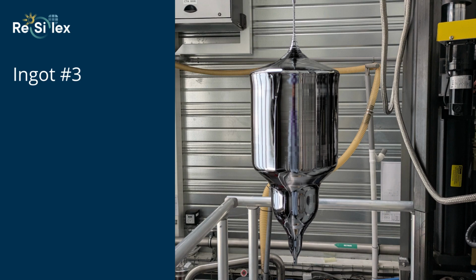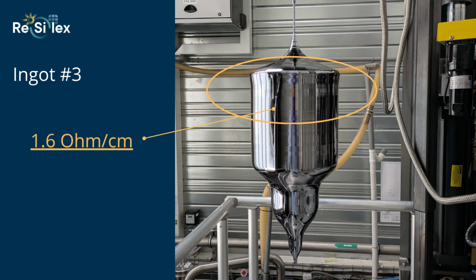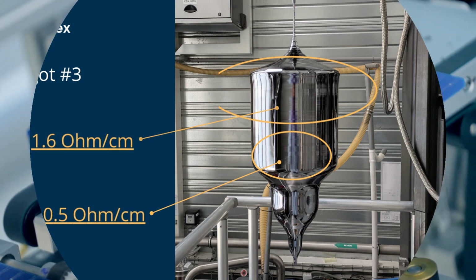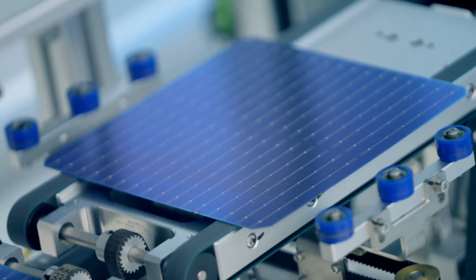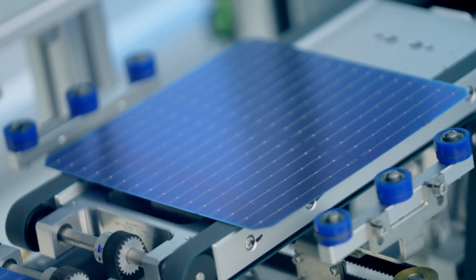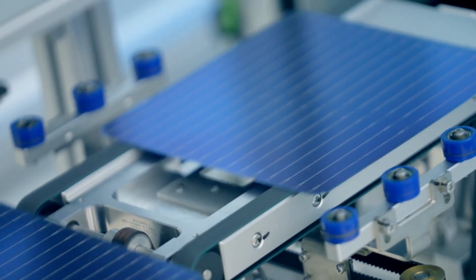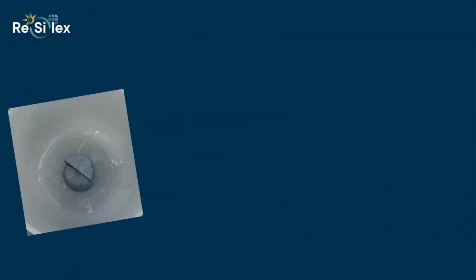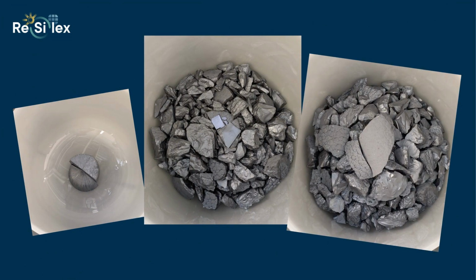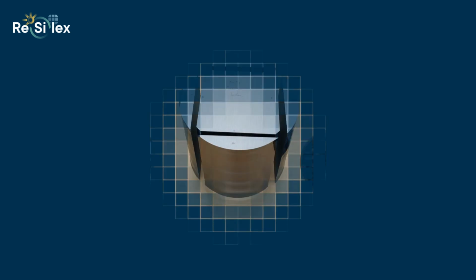The resistivity varies in this ingot between 1.6 ohm per centimeter at the head of the ingot and 0.5 ohm per centimeter at the tail end. This meets the resistivity and type objectives compatible with the manufacture of heterojunction solar cells on the CEA pilot line. For the first time, using a remarkable blending rate with 12% of high-purity recycled silicon.